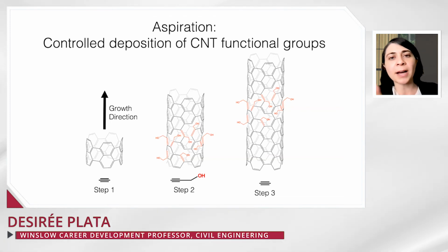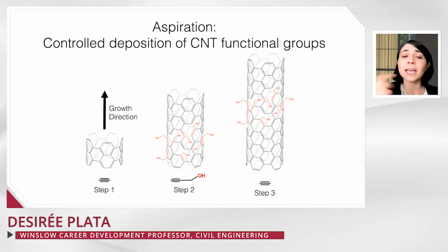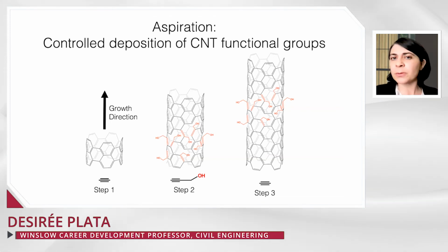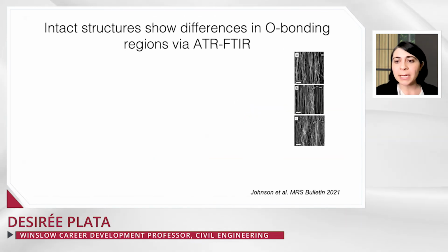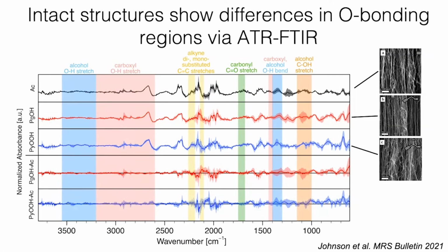This would allow you to deposit oxygen groups where you want them, and then maybe replace them with something else, whatever your desired chemistry might be. So when we looked at this and tried to interrogate it using attenuated total reflectance Fourier transform infrared spectroscopy, we were able to actually see the persistence of those alcohol and carboxylic acid groups into the carbon nanotube structures.